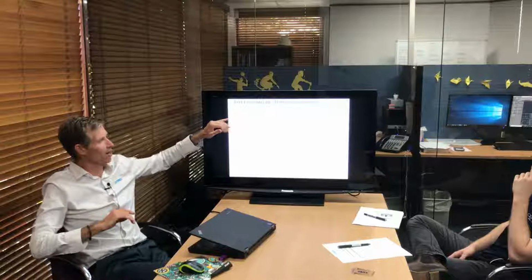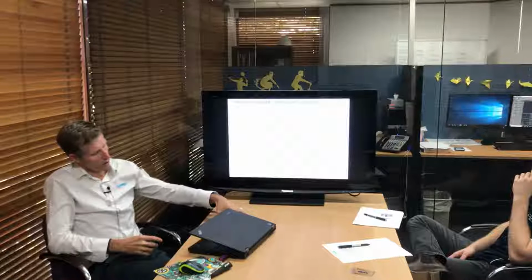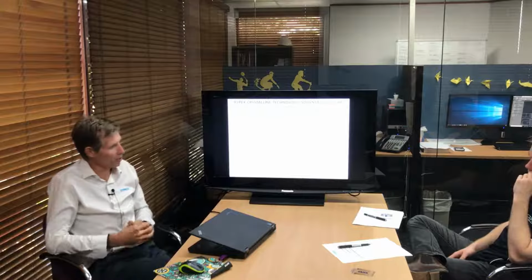Now we're going to touch on this chloride protection in marine environments in a field test in a minute, but we are able to show extension of life in the more aggressive marine areas, which would be in your C2 zone, the splash zone, where you get that heavy wetting and drying cycle. We do reduce the rate of carbonation, so as an admixture, you essentially eliminate it. As a coating, for a structure that's already in service, we can reduce the rate of that carbonation by almost about 35 to 40% from the information we've got.